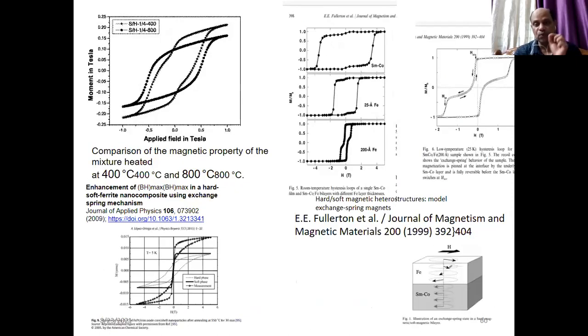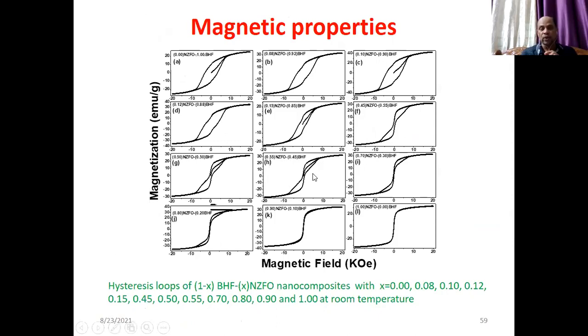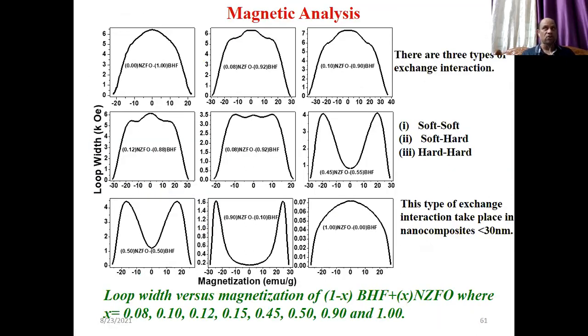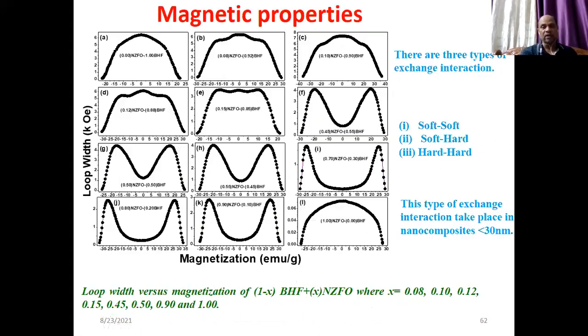The importance is, if you look into the magnetic properties, basically you keep your magnetization intact but reduce the coercivity for the soft magnetic application. That is the main intent for the application. But if I understand that they are biasing like that, I can choose the composition and tune the magnetic property so that I can get the material suitable for the magnetic applications. If you ask me which one is the best here, unfortunately, it is not the nanocomposite. The 50-50, we call it the boundary, that material, basically here or here, will be the best material for utilization, and not only for this material, they will be a better choice to be used in memory devices.